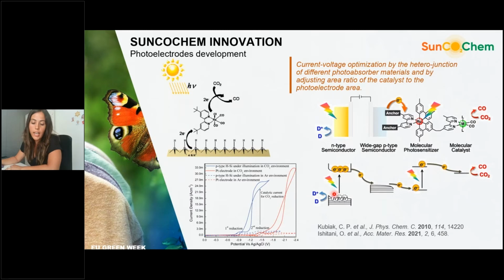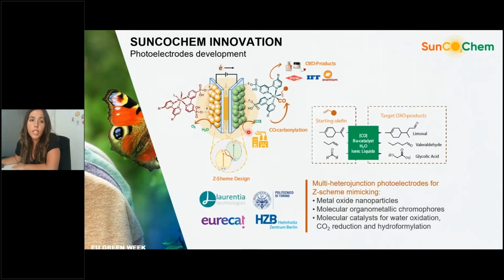On the other hand, the voltage of the cell will be limited by the band gap of the semiconductor that we use. So a single junction photoabsorber will not provide sufficient voltage for the reaction to take place. Here what we are doing is trying to combine different photoabsorber materials to obtain the required voltage that we need for the device. So the photoelectrode development in SunCoChem is based on a multi-heterojunction for Z-scheme mimicking in both the anode and the cathode, based on metal oxide semiconductor nanoparticles, molecular organometallic chromophores as photoabsorbers, and also molecular organometallic catalysts for the water oxidation reaction, the CO2 reduction reaction, and the hydroformylation reaction.